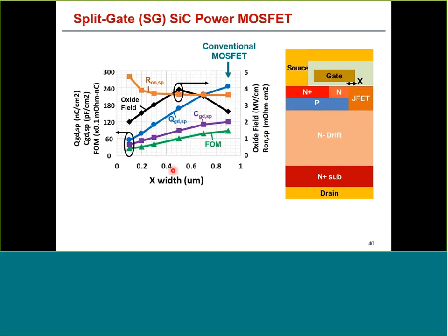Based upon these results, we believe that the optimum value for X was 0.3 microns because that's something we could fabricate at XFAB. I'm going to show you results achieved with that value.